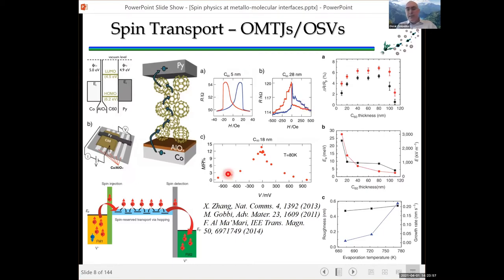A few years later, there was the paper from Zhang et al. in Nature Communications, where they demonstrated that this magnetoresistance in C60 was, surprisingly, not very heavily dependent on thickness, and they could see effects up to 100 nanometer thick layers. Again, very dependent on the applied voltage and on the actual roughness of the molecular film. Given that the molecules are relatively big, roughly 1 nanometer in size, it's difficult to make very smooth surfaces with them.